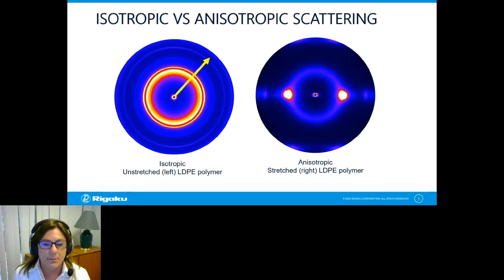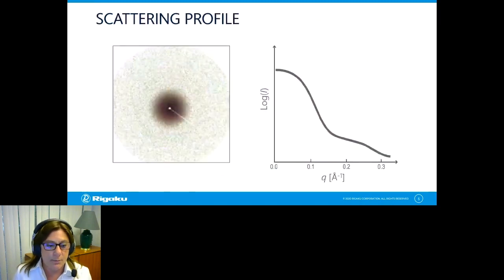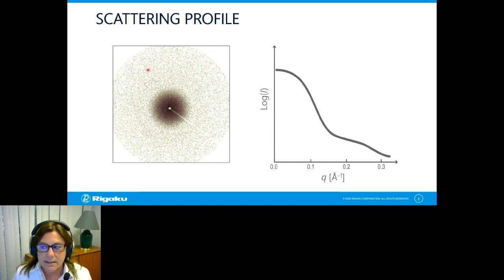So for example, the samples can scatter isotropically. What does that mean? It means that if we look at the scattering vector in this direction, it produces the exact same profile as one produced from this direction. Scattering can also be anisotropic. In that case, a scattering vector in this direction will produce a different scattering intensity profile from this direction. So that might mean that you integrate or you process data differently depending on how your sample scatters. So for example, here we can integrate across all angles. And in this case, we might instead just integrate across the wedge. And from that, we're going to get a 1D profile. So let's go back to our original scattering image. And here it is on the left. And if we integrate that across all angles, we get a scattering profile that provides the intensity versus Q. And generally, we'll look at the log of intensity versus Q or a log-log plot.